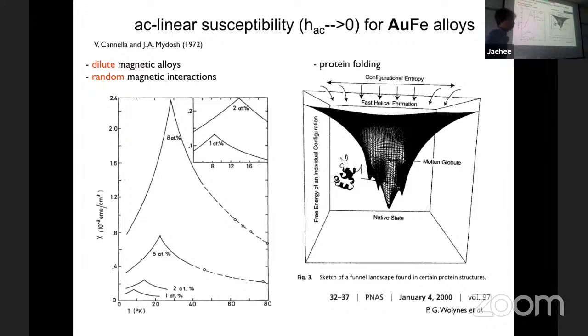Yeah, but still, this peak which you showed there is taken at zero field, right? Right. And what you see is that the susceptibility becomes largest at some characteristic temperature and then falls down. So usually that would mark some kind of phase transition or whatever. That's right. So what is happening here? That's a big issue in the ordinary spin glass, whether this transition is real. Sometimes people don't believe, sometimes believe this is a true transition, and some people say the true transition is at zero temperature and this is only due to relaxation.